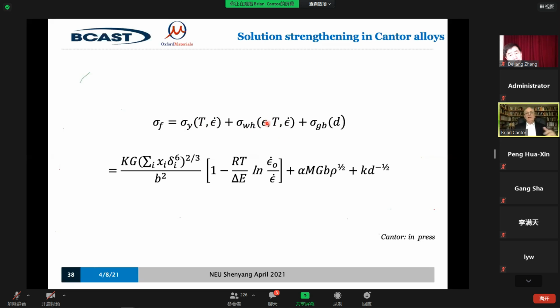So as you get the dislocation pileups, the flow strength gets higher: conventional work hardening, and a grain size effect, because if you make the grain small, the dislocations have to move through the grain boundaries. Now these two effects are well known, and they're no different between the multi-component alloys and the single component pure materials. This is what's called Taylor hardening.